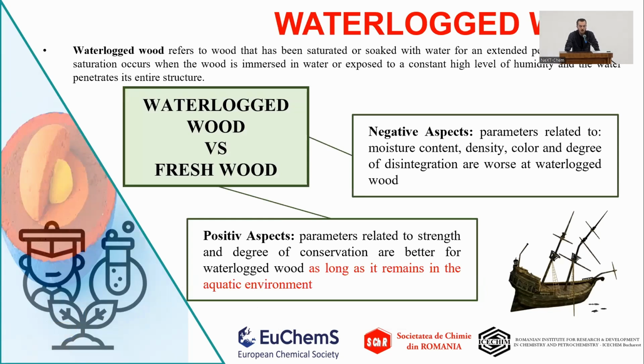Waterlogged wood refers to wood that has been saturated or soaked with water for an extended period of time. This occurs when the wood is immersed in water or exposed to a constantly high level of humidity, and water penetrates its entire structure. This process has some negative aspects and some positive aspects. The negative aspects are related to moisture content, density, and the color and degree of disintegration, and some positive aspects are related to strength and the degree of conservation, as long as it remains in the aquatic environment.